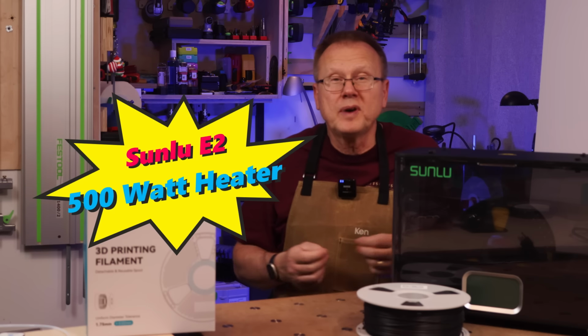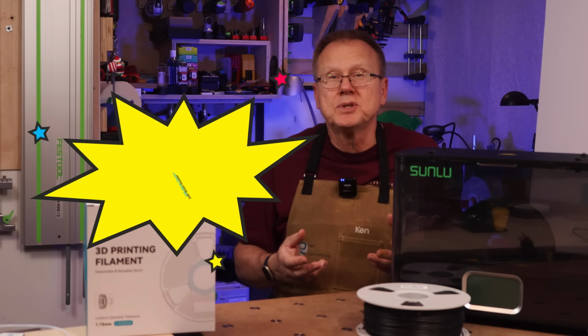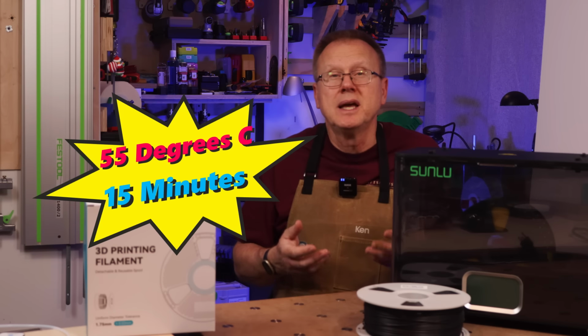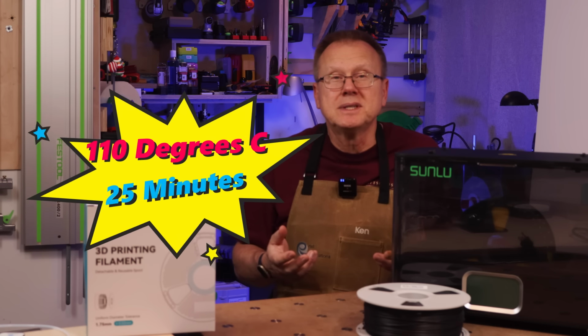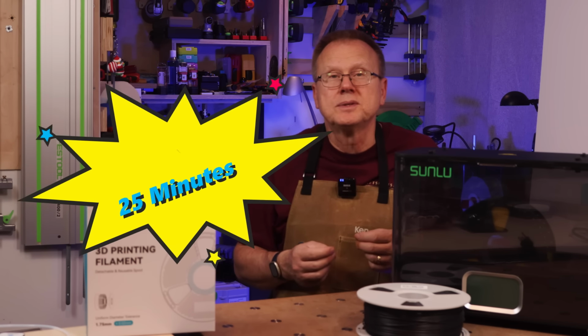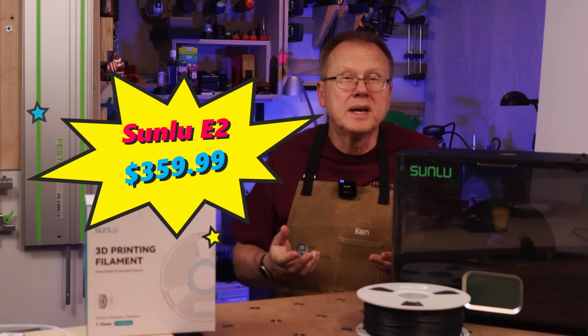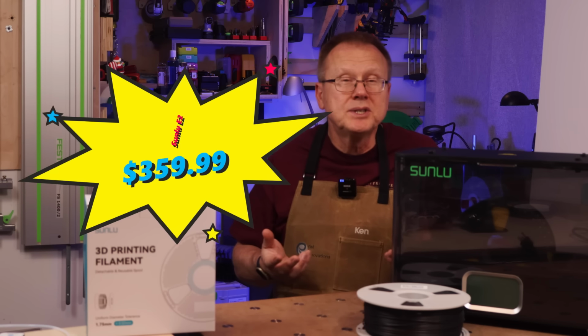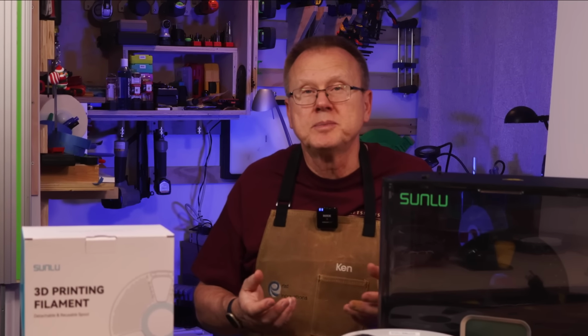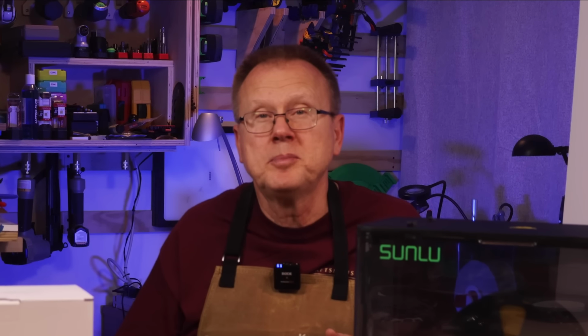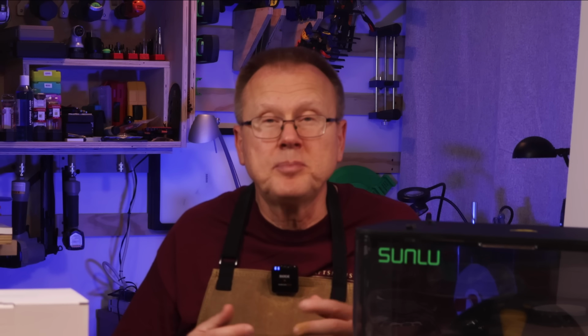It has a powerful 500 watt heater that heats up the chamber to 55 degrees C in 15 minutes and 110 degrees C in 25 minutes. At a cost of $359.99, it's not cheap. But if you are printing the higher temperature materials, especially PPA and PPS carbon filled, it's the best filament dryer to tackle those engineering materials.